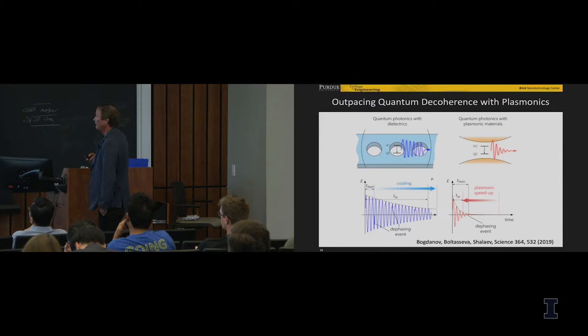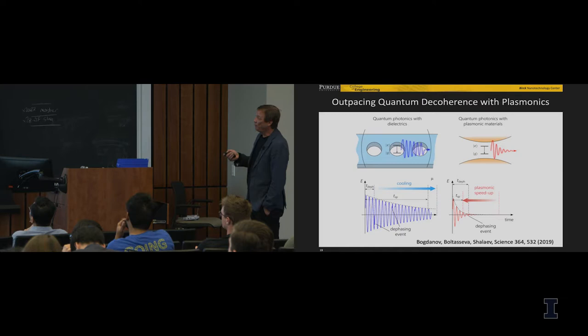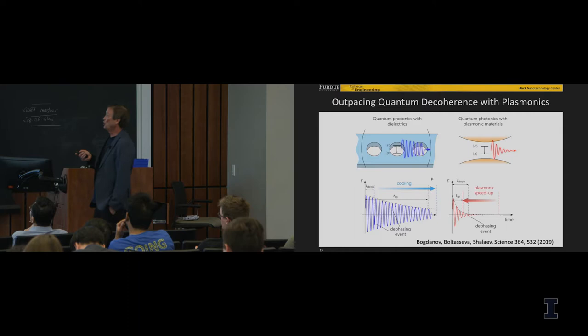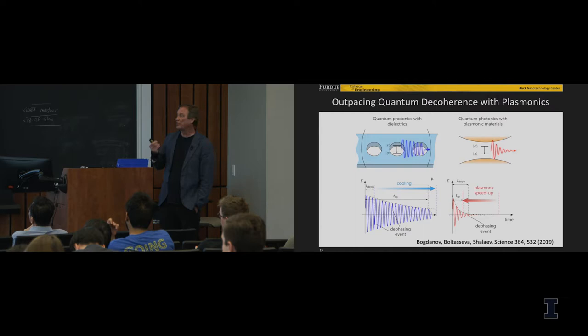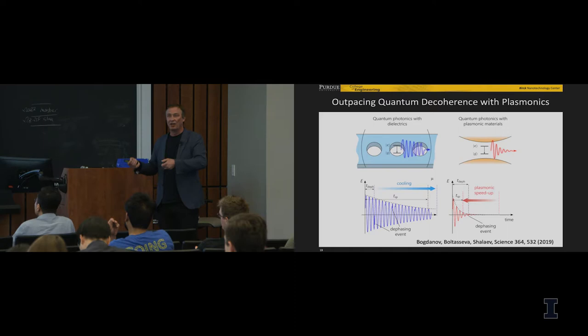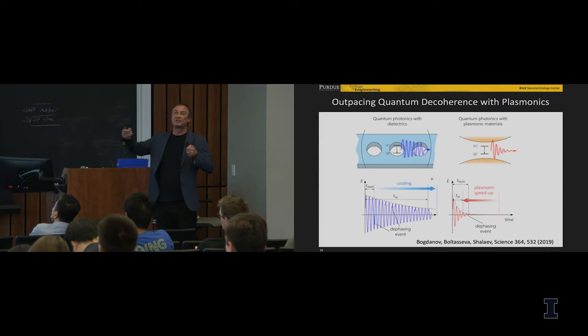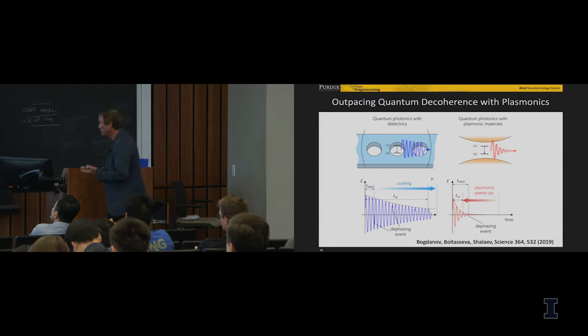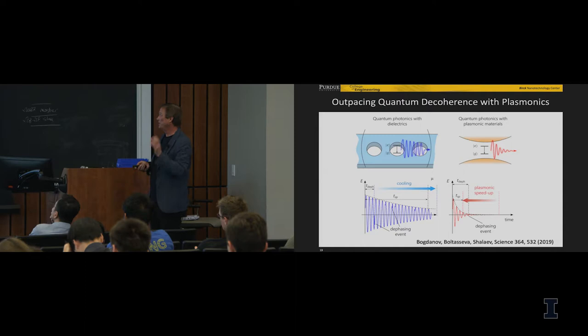Let's say with the conventional approach, when you have dielectric cavities, for example based on photonic crystals, you have this high Q, and to beat the decoherence process, you either trap ions or trap atoms, or go to extremely low pressures and extremely low temperatures so that coherence time increases, because you basically control your system as much as possible. What we are suggesting, instead of doing all these extreme things, is to let it go its way. Let's go to room temperature, where decoherence is particularly high and the rate is very high. But we speed up the process so that it happens before decoherence happens.